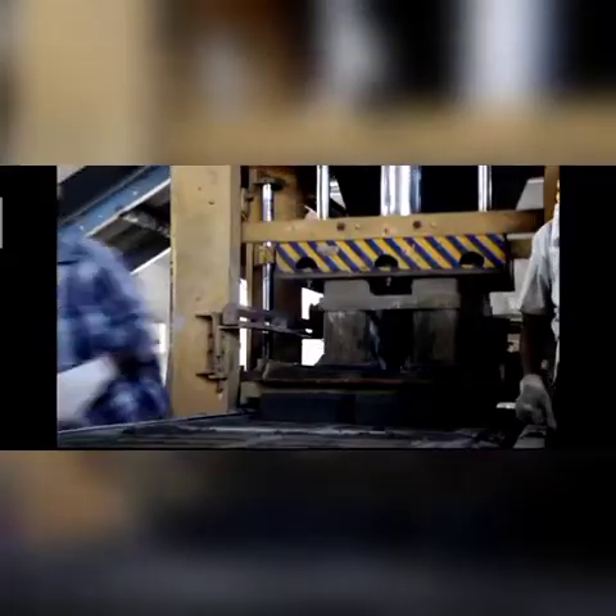Properly mixed raw material is generally transported through a belt conveyor to the press feed hopper. The mix is then fed to the hydraulic rotary press, where the molds are automatically filled. A set of two molds each is located 120 degrees apart on the rotary table. Bricks are formed at a pressure of 150 to 200 kilograms per square centimeter. In the case of a vibro press, the mix is manually brought from the pan mixer and then filled in molds. The table on which the molds are kept is vibrated. Generally, bricks made from both presses are of acceptable quality.